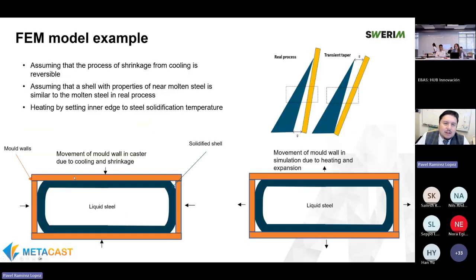From our side, at this very moment, I would like to bring up a FEM model example where we are taking the shells in a similar approach as taking these breakout shells, assuming that the shrinkage from cooling is reversible. So it's a very controversial approach, but it helps us to set easier boundary conditions for shell growth and shell resistance. In this case, we take it as a 2D slice, but this 2D slice is basically going upwards, or reversible, and then we are moving the mold in according to the actual taper for the wide side or for the narrow side, for those of you who are familiar with casting.